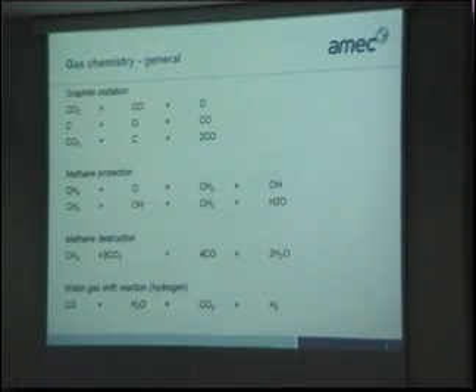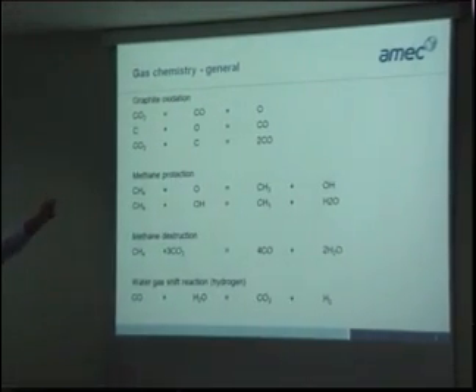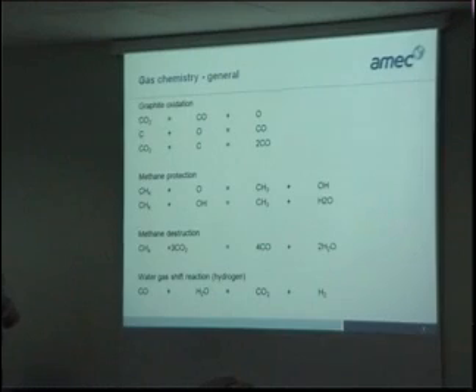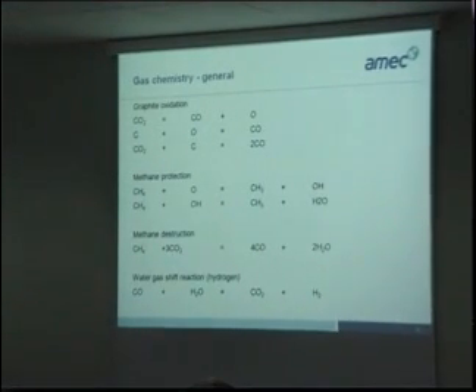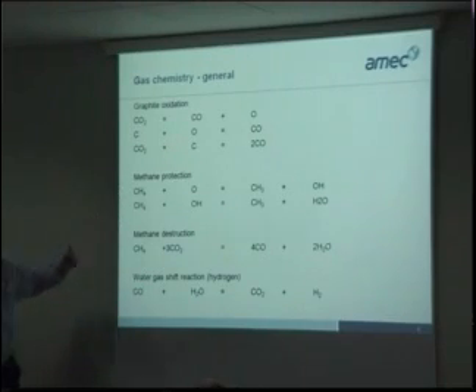CO2 at high temperature and pressure is an oxidizing agent. Under a high radiation field, it'll dissociate into carbon monoxide and oxygen atoms, and the oxygen atoms will in fact react with the graphite moderator. The graphite moderator over the years has gradually been disappearing, mass loss, but this is quite acceptable. It's reviewed every year, and so far we're doing okay on graphite mass loss, but it forms carbon monoxide, and furthermore the CO2 could also react with the graphite directly to form carbon monoxide.